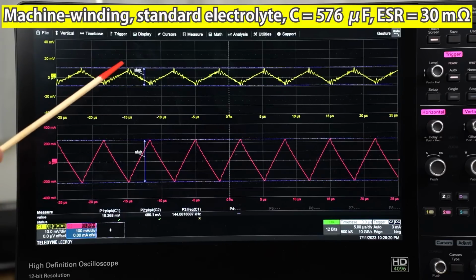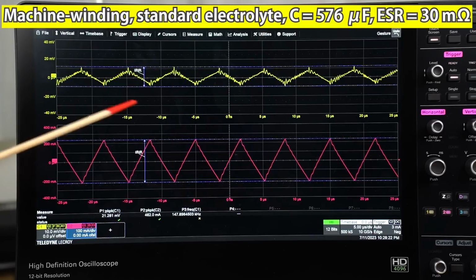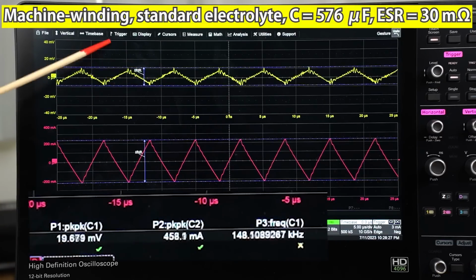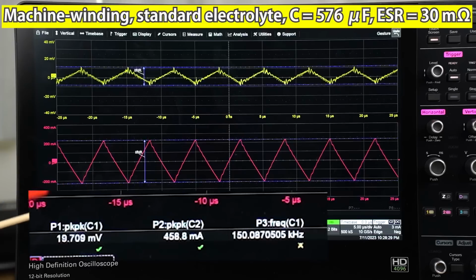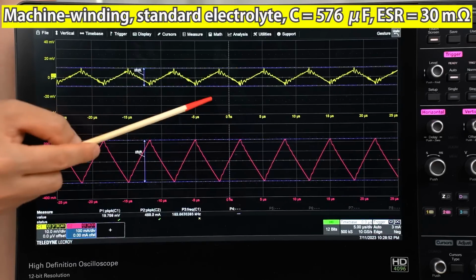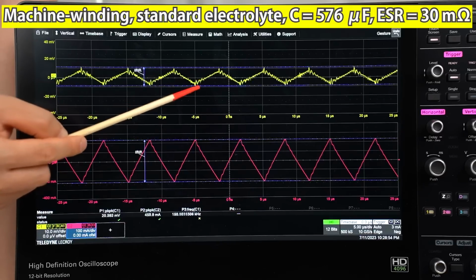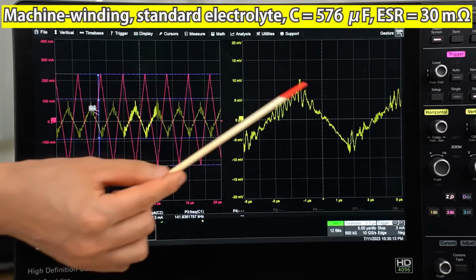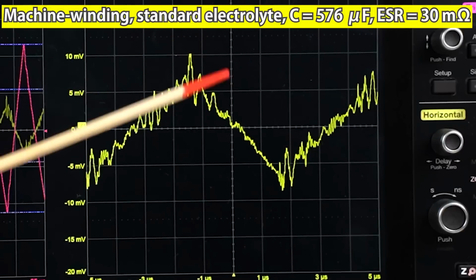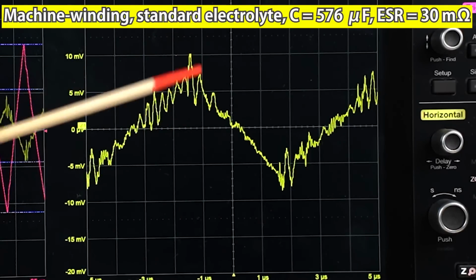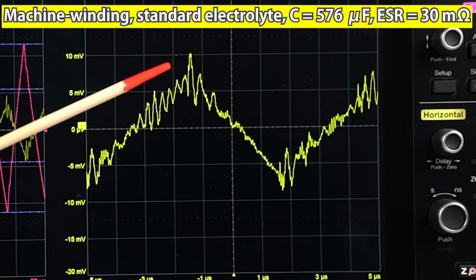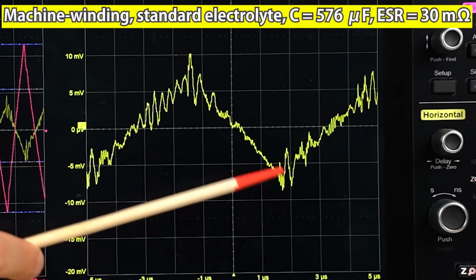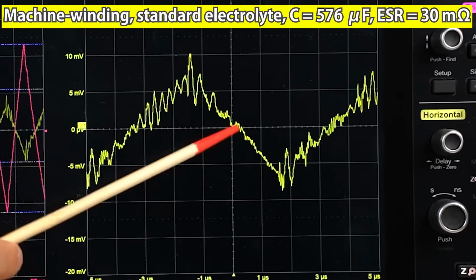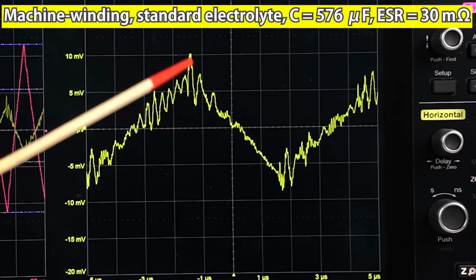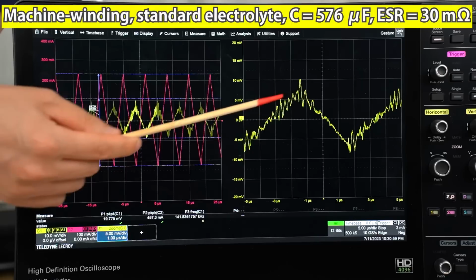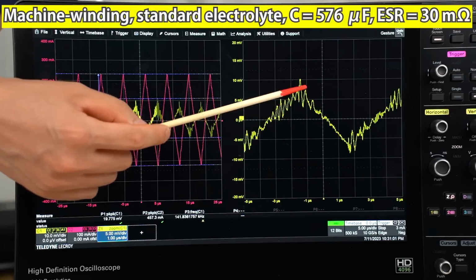Compared to my hand winding one, the capacitance is only about 70%, but the peak-to-peak ripple voltage is almost the same, around 20 millivolt. It seems the ESR and ESL are affecting the ripple more than the capacitance. I enlarged the ripple voltage waveform. There's a slight surge voltage at the point where the switching occurs. It's caused by the ESL. It's hard to find the part affected by the ESR. There are some ups and downs here. They are caused by ESR. You can't see much influence from the capacitance.